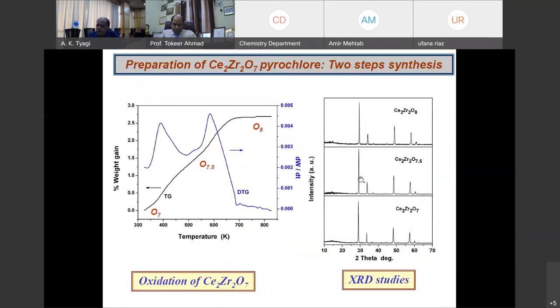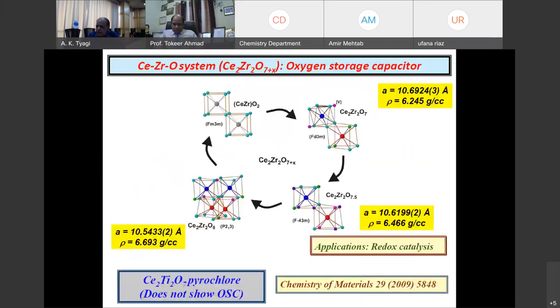You can see we made a new pyrochlore, Ce2Zr2O7. This compound has cerium in 3+ state, and you oxidize from O7 to O7.5, then to O8, and here lies an important result. So O7 becomes O7.5 and O7.5 becomes O8. So clockwise, this compound is able to pick up oxygen, and anti-clockwise, this compound is giving oxygen.